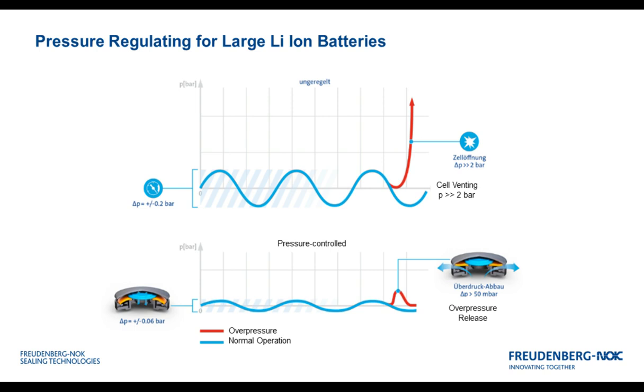As you can see pictured here on the top, we have an example of a pressure graph of an unregulated pressure housing, and this would be the blue line. You have the normal pressure cycles of the daily increase and decrease in temperature. The pressure inside that housing would increase and decrease with a sealed housing. And then in the event of a lithium-ion cell venting, you would see a large volume of gas be released very quickly, causing a very high pressure spike in that system. And this could potentially cause damage or worse to items on that pressure housing.